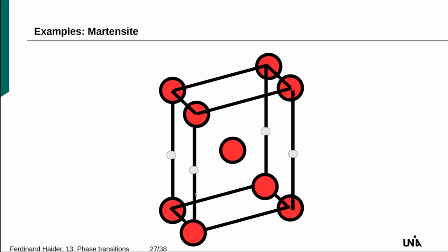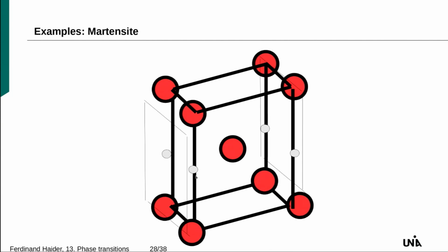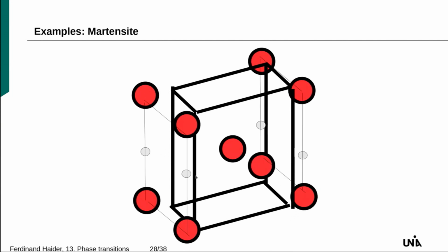And now if you do this transformation, the carbon sitting here, I mean not each site is occupied, only a small fraction of the sites is occupied. This prevents the transformation into this complete cubic phase. So it stays a bit tetragonal.